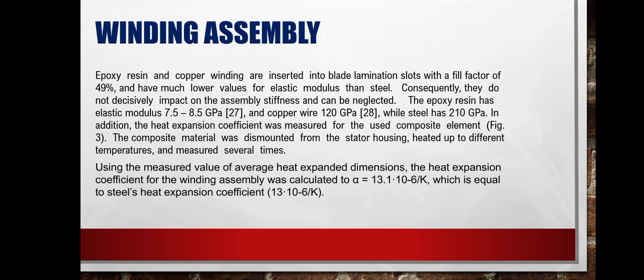In addition, the heat expansion coefficient was measured for the used composite element. The composite material was dismounted from the stator housing, heated up to different temperatures and measured several times to obtain the average heat expanded dimension. The heat expansion coefficient for the winding assemblies was calculated as alpha equals 13.1 times 10 to the minus 6 per kelvin, which is equal to steel's heat expansion coefficient.